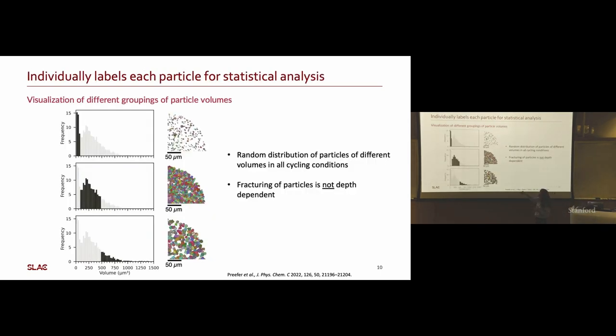So they're histograms, essentially. And the first thing we did was look at the volume of all the particles. And this is just the total histogram. And we've highlighted three different regions: the smallest particles, medium particles, and largest particles. We wanted to see where those were located in the thickness of the cathode, because we thought maybe particle cracking would happen more at the surface where the cathode is closest to the anode, because those are the ones that are going to be charged and discharged more easily because they're closer physically to the anode.